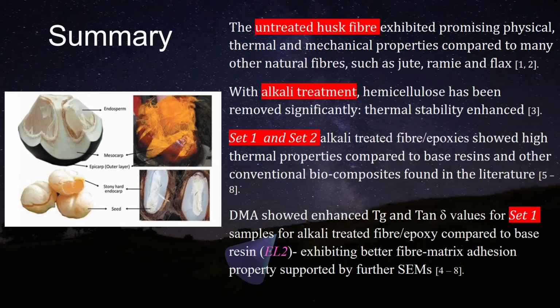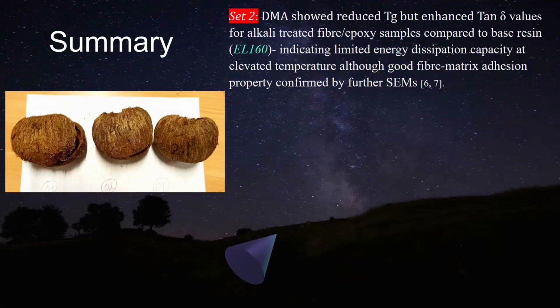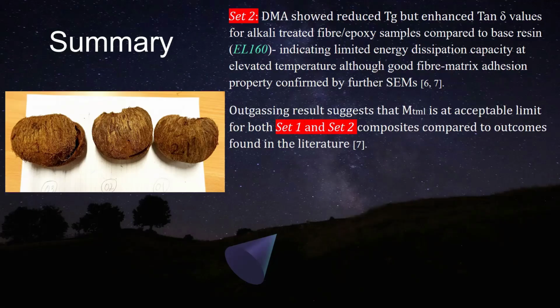For the set 1 sample, the alkali treated fiber got higher Tg value, glass transition value, and damping factor value, exhibiting better fiber matrix adhesion property, and that was supported by the SEM. But for the set 2 sample, the DMA showed that the Tg value reduced for the fiber-reinforced epoxy, although it is treated, but tan delta, or the damping factor value, enhanced for the biocomposite samples, indicating limited energy dissipation capacity at elevated temperature, although good fiber matrix adhesion property was confirmed by the further SEM we found.